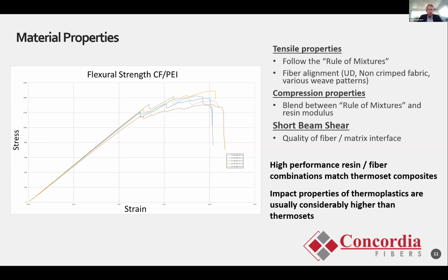But essentially, there's really too many combinations of thermoplastic and fibers and volume fractions and so forth to be presenting numbers up here, but I'd like to look at the overview by, let's say, looking at the tensile properties and the rule of mixtures. Something like the rule of mixtures does a really good job predicting the tensile modulus. And with all composites, it's not as easy to come up with the tensile strength, but it does work pretty well. And then for compression properties, it's really a blend of the rule of mixtures and resin modulus. If you end up using low performing resins, it's going to be not as good as using high performing resins.